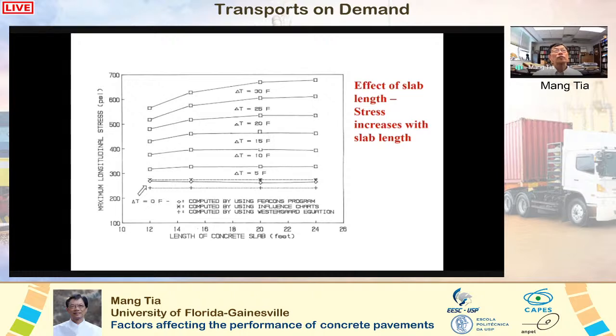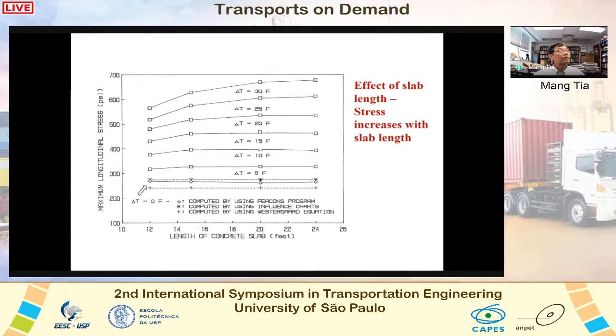When temperature differential in a concrete slab is not considered in the stress analysis, slab length has no effect on the maximum stresses. However, when there is a temperature differential in the concrete slab, the concrete length could have significant effect on the maximum stresses. These are plots of maximum stress in a concrete pavement as a function of slab length for different temperature differentials. As you can see from these plots, when there is a temperature differential in the concrete slab, the maximum stress increases as the slab length increases.